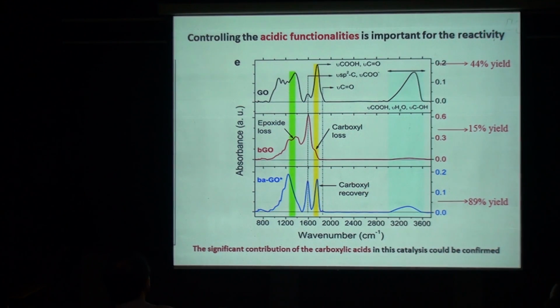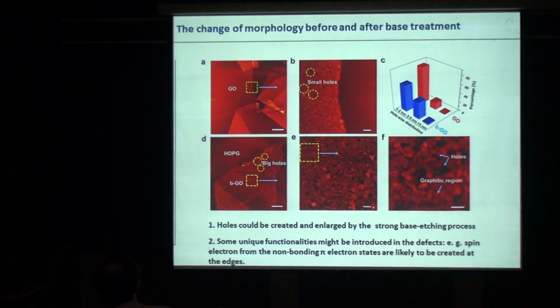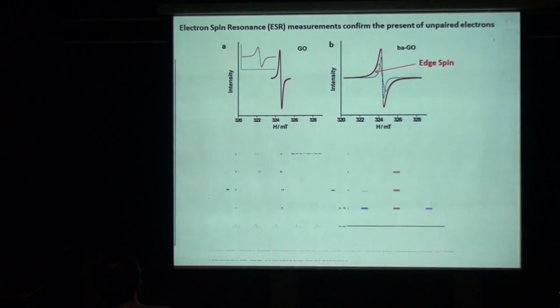Again, and at the same time, the carboxylic group, COOH, for people that are familiar with chemistry, if you take an aromatic platform and try to transform one carbon to COOH, you find that you can't do it, you see. You can transform to C-OH or two carbons with an epoxy group, but to make a carbonyl, C double-bond O, and then with the OH, you cannot at the basal plane. You can only do it for the edge carbon. So the COOH can only exist at the edge and not on the basal plane. And the COOH group is also very important.